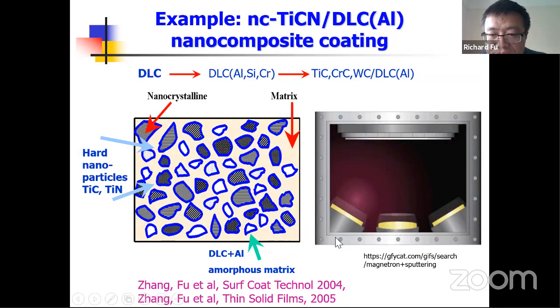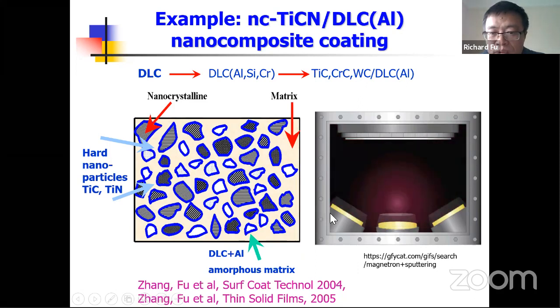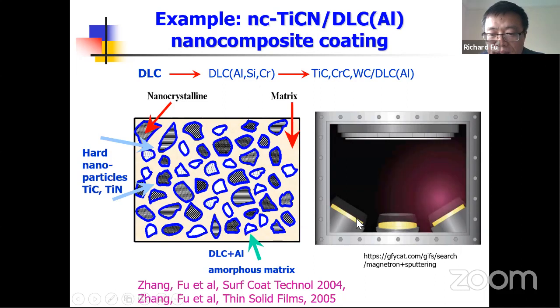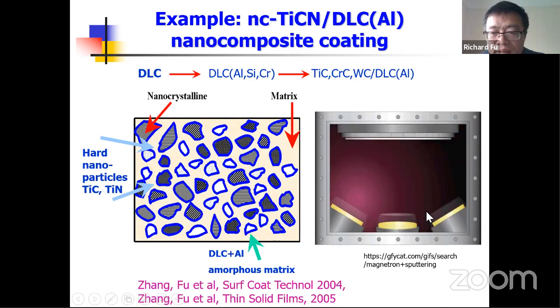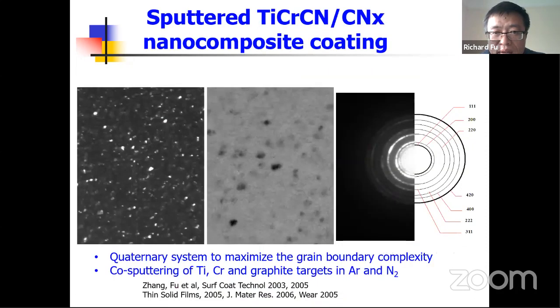So how to realize it? We normally use magnetron sputtering. We use multiple targets, for example a carbon graphite target together with metal targets, within a gas mixture of argon, oxygen or nitrogen. There is a lot of optimization of the parameters. The process parameters, including power, gas ratio and pressure, can be controlled. Then we can achieve, within a matrix, a lot of small dots which are nanoscale. Because it is nanoscale, the electron diffraction pattern is normally a ring pattern, which shows the structure.